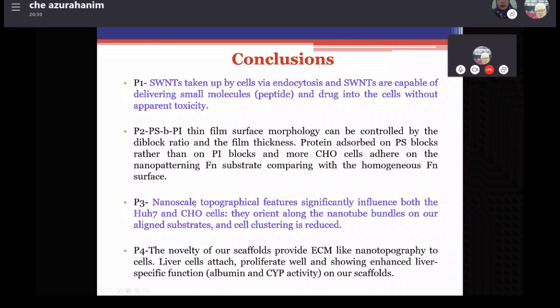For this one, we developed nanoscale topography features that significantly influence both the HUH7 and CHO cells. Actually, for the third project, I should have used cells that really need the aligned orientation, but at that time I didn't have those cells, so I just used whatever we had in our lab. In the fourth project, the novelty of our scaffold is that it provides an ECM-like structure. That means we found that the liver cells, actually I am only showing you HUH7 cells. I have papers, maybe I can send you the list of papers already published from this project, because for the fourth project we published in 2014 the paper on primary rat hepatocytes attached on the 3D cell culture based on CNT yarn.